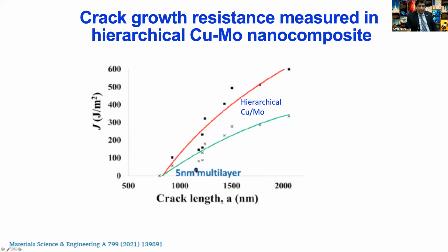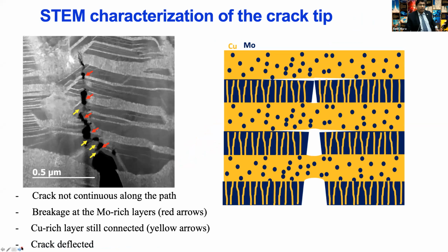For the case of multilayer, there is just one dot because the sample failed as soon as the crack formed. So there is no resistance, there is no R curve behavior. The resistance does not increase as the crack length increases. But for the case of the hierarchical microstructure, there's a significant increase in the strain energy release as the crack propagates across. That had never been shown for these kinds of very fine scale multilayers. So it's very promising. Of course, there's some scatter depending on how you measure the yield strength, but it is very promising to see this kind of a crack growth resistance.